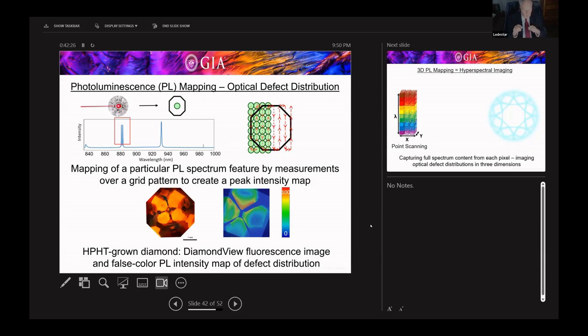shown at the bottom. So on the left is a fluorescence image of a high pressure, high temperature grown synthetic diamond, as you see in an instrument called a DiamondView. You see a crosshatch structure, which is a characteristic feature of a synthetic diamond. And on the right, you have a false color PL intensity map of the distribution of the defects, which again correspond very closely to the structure of the diamond. And it's amazing to me that you have a technique that allows you to look at atomic level defects and their distribution. But we've actually now gone one step farther.